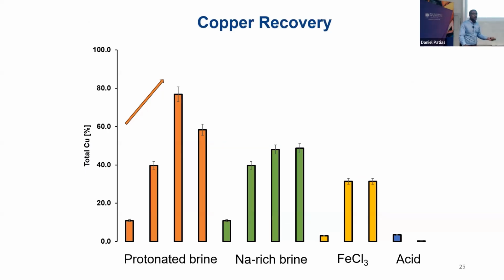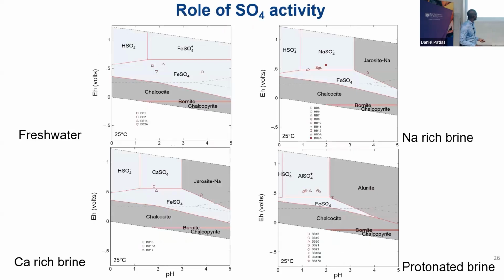So we then went ahead to optimize what we saw. We did further leaching tests just to see what's happening in the system. Under all conditions, when I say all conditions, I mean varying temperature, varying pH and the likes, we can tell there's much more copper for the protonated brine lixiviant compared to if you use sodium chloride rich brine, ferric chloride, or acid. And that was really interesting.